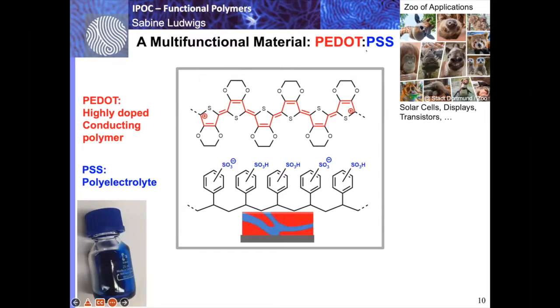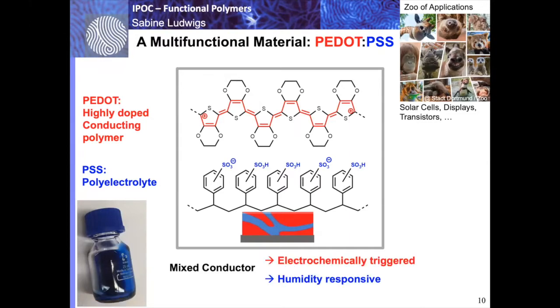And this PEDOT:PSS polymer has found a number of different applications. It's one of the workhorses of the flexible electronics community, for solar cells, displays, transistors. So PEDOT:PSS is heavily used in that. We were more interested in their genuine properties. On the one hand, it is this electronic conducting polymer, so it can be electrochemically triggered and changed in terms of doping state. And on the other hand, it is also humidity responsive, because this is the polyelectrolyte, which gets ionically conducting as a function of humidity.